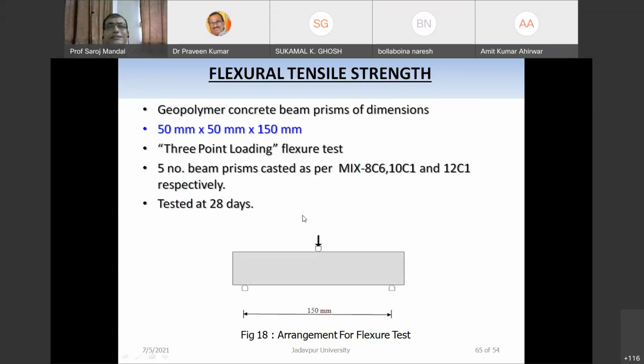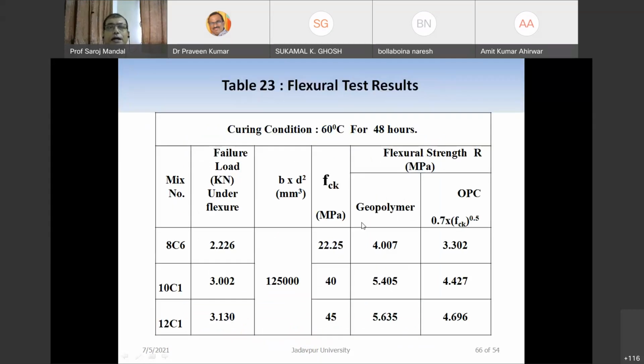That is the 3-point test. We are taking the sample of 50 into 150 with 3-point loading. If you see here, your failure load is like this, and the FCK values are already known, and we got the geopolymer testing values. And for OPC, if we take 0.7 root over FCK, the values are like this. So in the case of geopolymer, we comparatively get higher values of flexural strength compared to normal OPC.